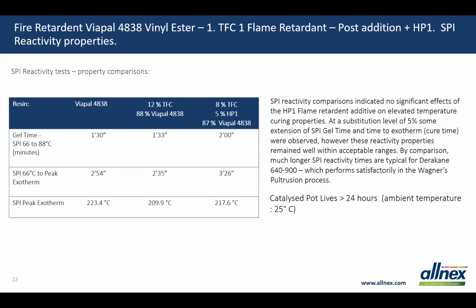On the reactivity side, we didn't actually see any issues there. No significant effects that it had on the material at all. The increase in gel time is not regarded as significant, so curing under the elevated temperature curing conditions were comparable. And I mentioned Derakane 640-900 is another resin that shows much wider range, or much longer SPI gel times, and that still works quite well on the Wagner's line. So we know for a fact that these SPI reactivity values are still virtually unaffected by our experience.